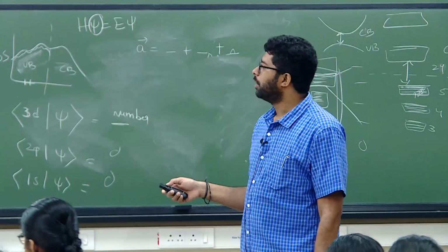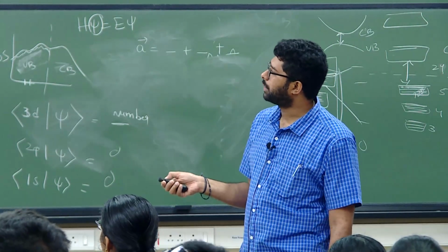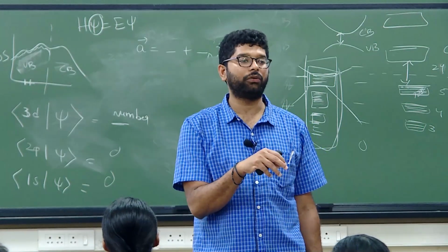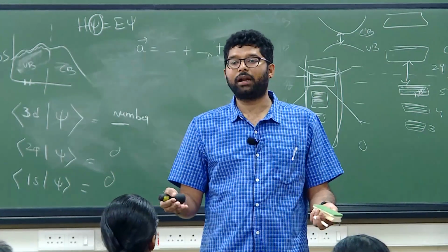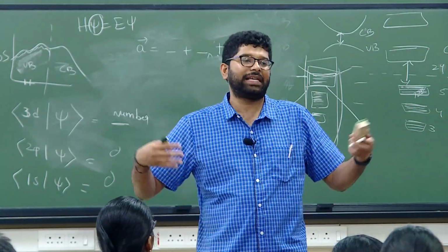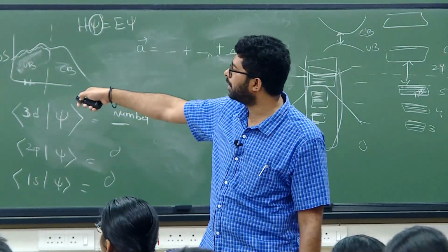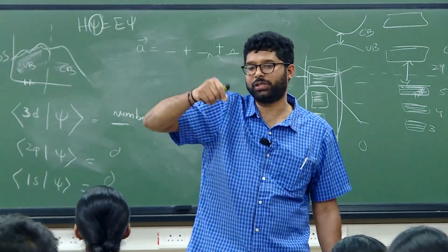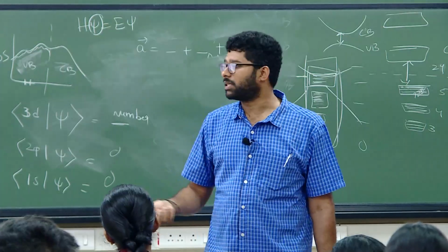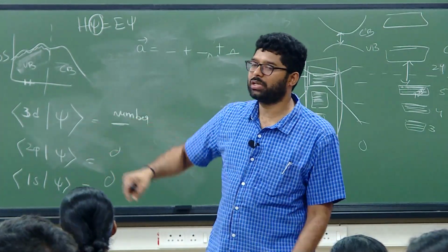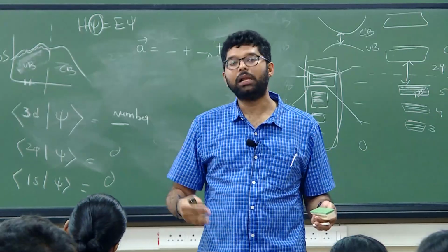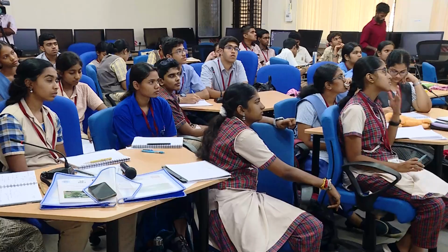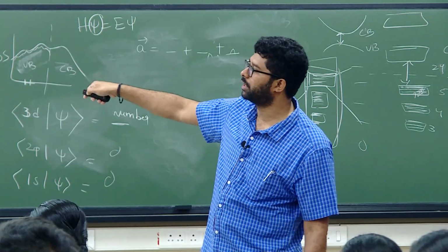Okay. Apart from this, what we also need to understand is the adsorption. If the metal is strongly adsorbing, then it will not allow you to form dendrites. So now your system is there. How do you find the most stable adsorption site? There are several possible adsorption sites. We considered about 12 or so. Among them, 6 we could optimize. These are the 6 positions we were able to keep. Among these 6 positions, we observed that S3, S1, S2 are the 3 sites where the system is very stable. The other 3 fall back to the same things. So the order of adsorption is S3 greater than S1 greater than S2.